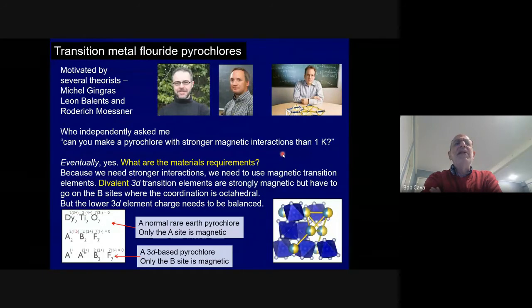Okay, so it may have taken me 10 years to figure out how to do this, but eventually we did it. And it has to do with asking what are the requirements for the materials that you would need to make the magnetic interactions higher than 1 Kelvin so people could study them. Well, the magnetic transition elements, which are 3d elements, are much more strongly magnetic than the rare earths. You know that 3d elements like cobalt and iron and nickel make magnets that stick to your refrigerator. So magnetic ordering can happen at much higher temperature. And the highest magnetic moments are typically what you get with the 3d series of transition elements, where the unpaired electrons are in 3d orbitals, so they're not hybridized too much with their ligands, and they need to be 2+ transition elements to give you strong magnetism.